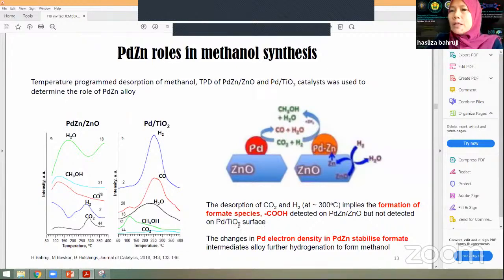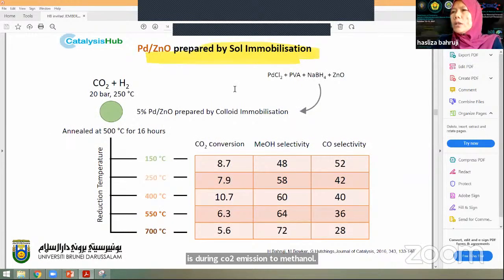What this tells us is that the desorption of carbon dioxide and hydrogen implies the formation of formate species, which is only detected on palladium zinc alloy, not on Pd/TiO2. It gives us indication of the importance of palladium zinc alloy to stabilize this formate species during CO2 hydrogenation to methanol. And this is how we improve the properties of the catalyst by increasing the reduction temperature. We can see that the most active reaction is at 400 degrees Celsius, which gives us high conversion and high selectivity.